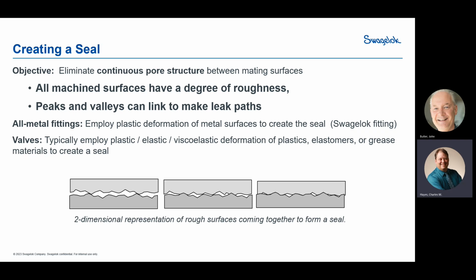Because when you have two hills hitting each other, you have valleys that now cause pores, or a porous structure. What can happen if there are enough of those is that you create a continuous pore structure where gas can flow between all these little voids at your sealing area and cause leaks. The size of that leak can be determined by measuring how much gas can pass through there.